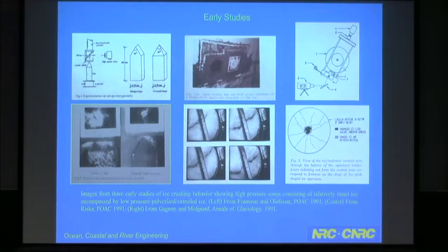This apparatus, I find it interesting, these three papers came out in the same year. This paper was what I did with John Mulgard. We were actually studying crushing friction. We had a rotating wheel here, and we were crushing an ice sample against the rotating wheel. At one point, we had the idea, let's have a look at what's going on at the interface between the ice and the wheel. So we cut a hole in the bottom of the ice holder and put a thick glass plate in there so we could look through the glass and the ice.